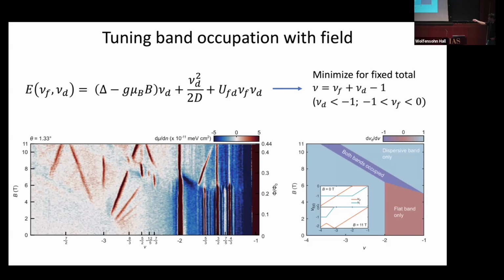You prefer electron solids when you're occupying these very, very flat electronic bands. The Coulomb repulsion is very strong and stabilizes those states. On the other hand, as you're occupying the more dispersive bands, you see Hofstadter states dominating. You have an electron liquid situation. So these are realizing these two different limits all in the same sample, just tuned by changing the relative energies of different Moiré bands. And maybe the most interesting thing, or most unique thing, is this little purple strip here,